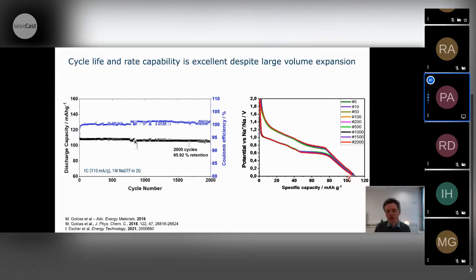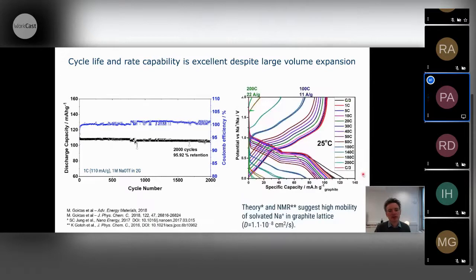One drawback of this approach is obviously, when you look at this value here, we are limited to around 110 milliamp hours per gram. Right? So this is not perfect for a battery. We want to be higher. So we look for solutions in order to increase the capacity of these materials.